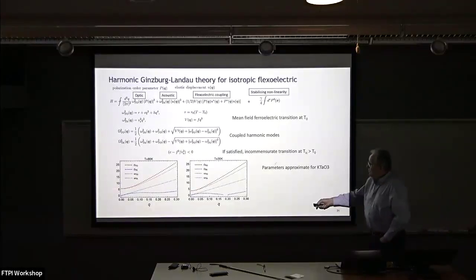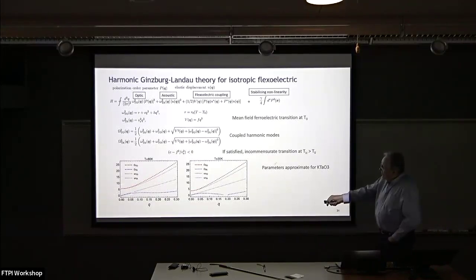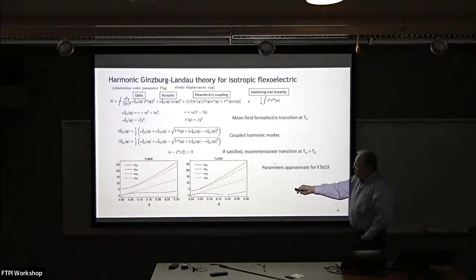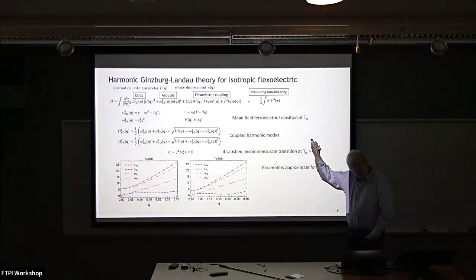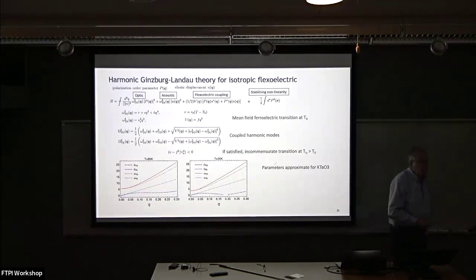But one should also remember that there's an acoustic mode. There's no coupling between these modes at Q equals 0, but the coupling turns on at finite Q. And so what you can see, of course, is that as you cool and the temperature comes down and this mode gets soft, it's going to push on that acoustic mode. If that coupling is big enough, you can drive the acoustic modes soft. And I'd like to take that as a hypothesis and come back to see if that works. Now, this isn't a new idea. If you look at many classes of ferroelectrics, quartz is one.